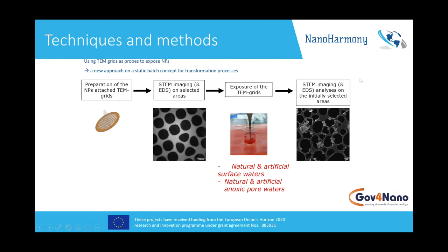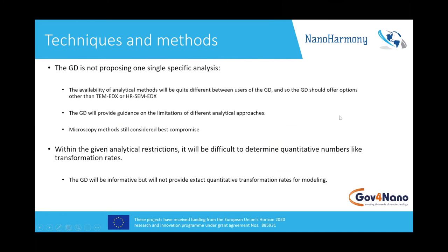For the techniques we want to apply, the core method will be attaching particles to a TEM grid. We take the unexposed grid into the TEM and locate certain regions where the particles sit. We then expose the grid to certain conditions and re-examine the particles at the same locations again, monitoring with EDX analysis for morphology, shape, and size — monitoring the change and transformation of the particles. This will be our core method.